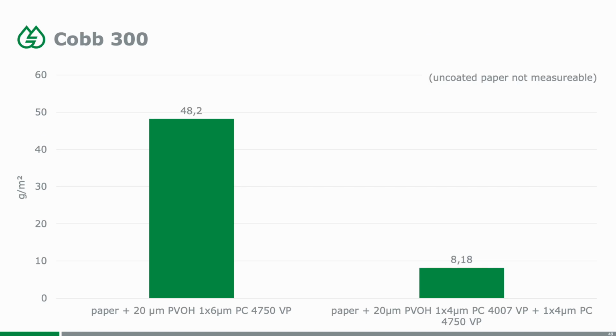Then we also need to check the COBB resistance. In this case, we cannot compare to uncoated paper because that was simply not measurable. That shows you how weak the water resistance actually is. And the paper with the PVOH and the PC4750 in a COBB 300, we are getting to 48 grams per square meter, so that's actually quite high for the short period of time. But then again, if we use a two-layer system, we'll bring it down to 8. So we are able to make a coating on the PVOH which does not destroy the O2 barrier, but which gives you additional protection against water and moisture.